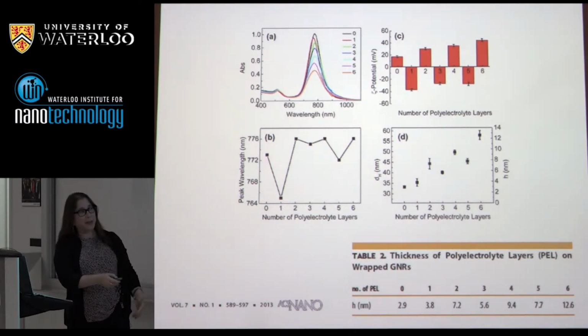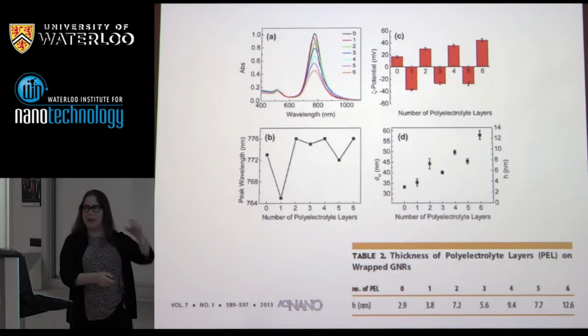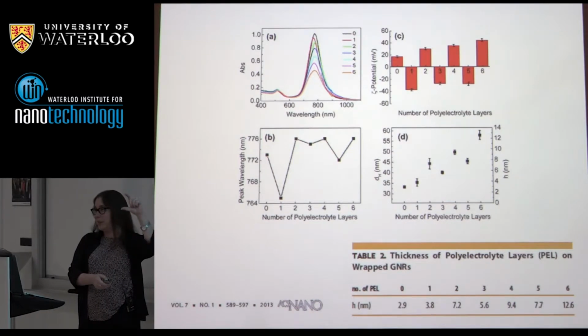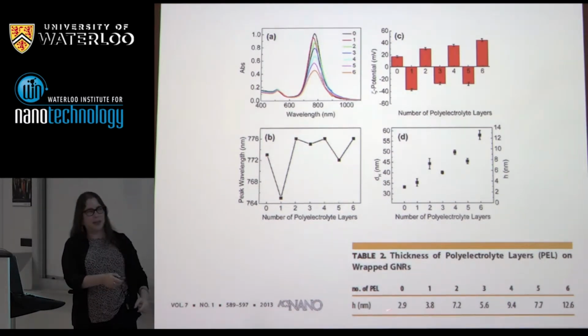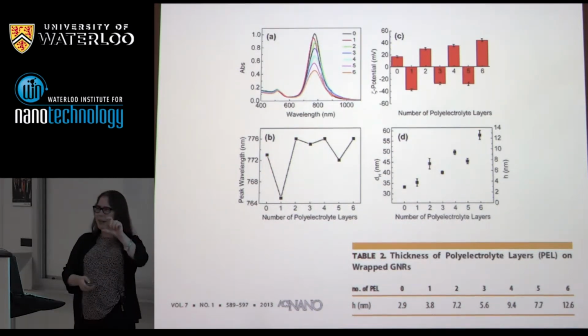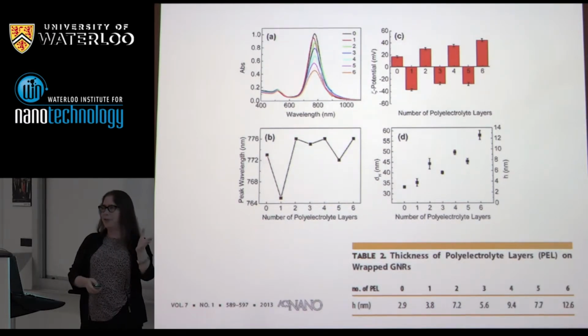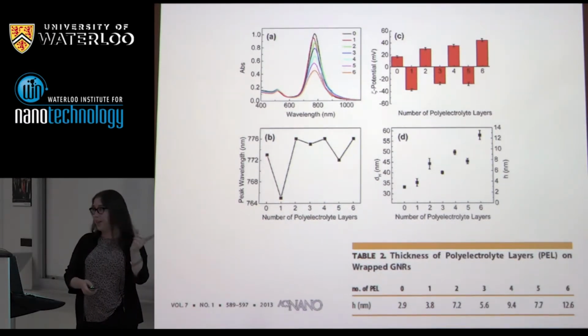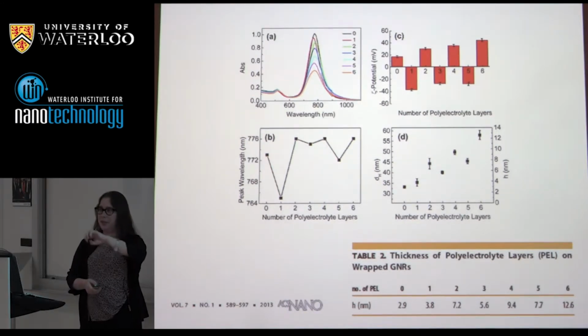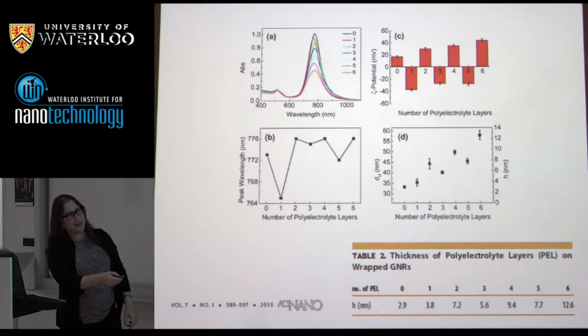On our surfaces, when we do this, this is a dynamic light scattering experiment. It's probably easiest to look at this table down here. So without any polyelectrolytes, CTAB all by itself, a molecular model would say 3 nanometers thick is that hydrophobic region. The experiment here says 2.9. By the way, this experiment is coming out of light scattering. It's a little bit of an interesting experiment. Dynamic light scattering, if you've ever done it, the number you get out for the size assumes everything is a sphere, which we know we don't have here. But if you know you have an anisotropic shape by TEM, you can go ahead and get the coating thickness. There's a little formula Luis Liz-Marzán developed for the coating thickness of your layer using this simple experiment. So that's pretty handy.